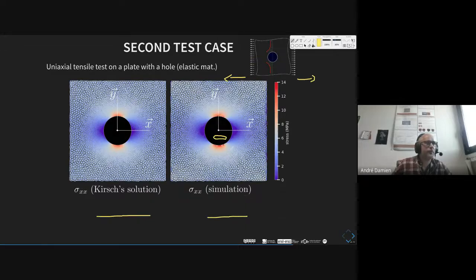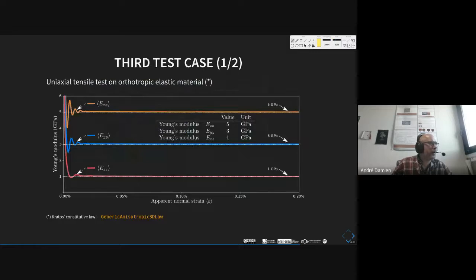So another test now is to test an orthotropic elastic material. This is a very open problem with the discrete element method. At this time, I don't see any satisfactory way to deal with orthotropic elastic material. Here we simply use the generic anisotropic 3D laws of the Kratos package. As you can see, we put 5, 3, and 1 gigapascal on the Young's modulus on the x-axis, y-axis, and z-axis, and we get apparent values which are very close to what we put inside as input parameters of our simulation. So it's a good result.